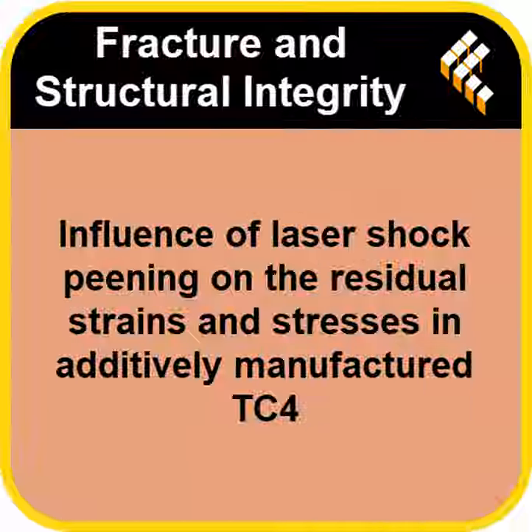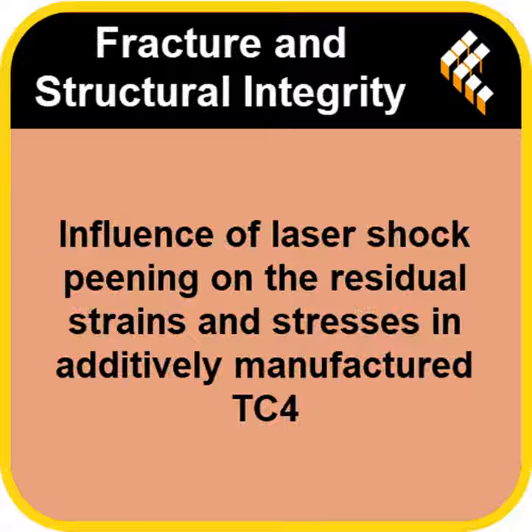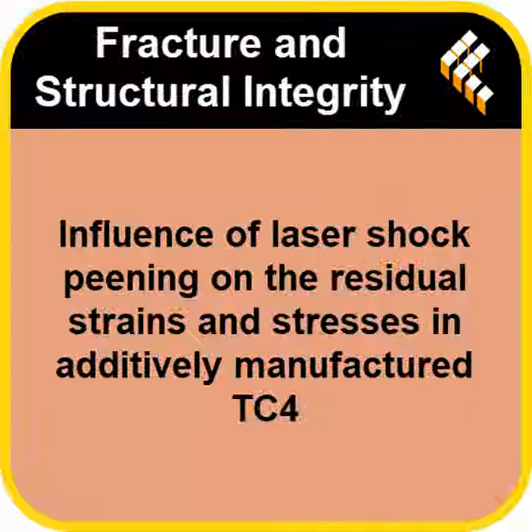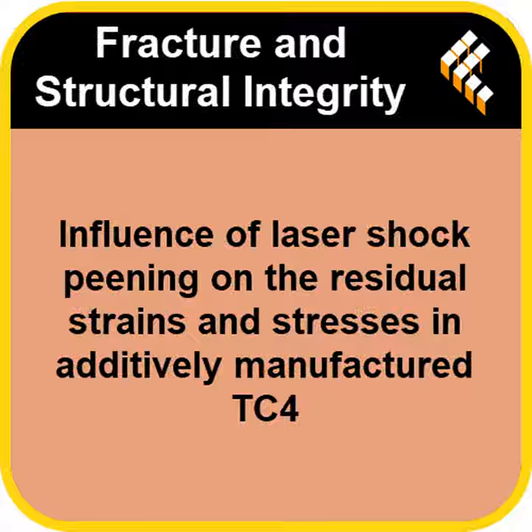Okay. As the hole gets deeper, the rosette precisely measures how much the surface strains or relaxes in those 3 directions. So you get strain readings at different depths. Right. And crucially, because LSP creates stress that changes with depth, they can't just assume it's uniform. They have to use a calculation method, the non-uniform stress field method, that accounts for that variation. That sounds complicated. But it gives a true picture of the stress profile. It does. And remember, if the strain gauge measures a positive relief strain when the hole is drilled, that means the original stress was compressive. The good kind. Success. Precisely.